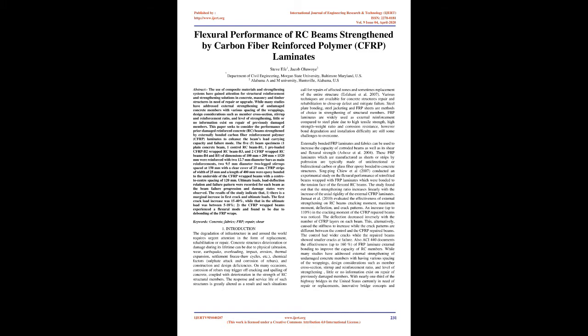B3, and 2 CFRP wrapped RC beams B4 and B5, of dimensions 100 mm x 200 mm x 1520 mm were reinforced with two 12.7 mm diameter bars as main reinforcements, two 9.5 mm diameter two-legged stirrups spaced at